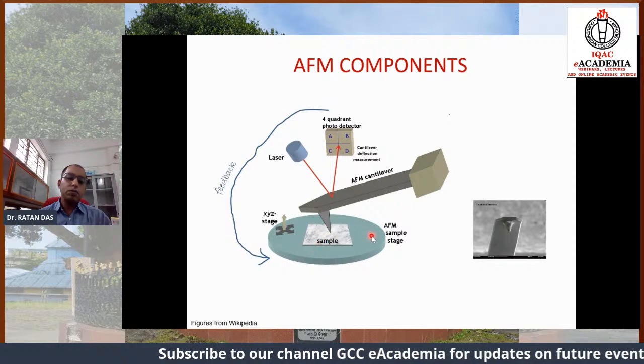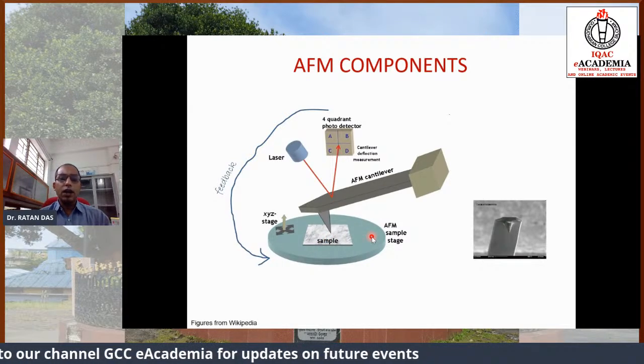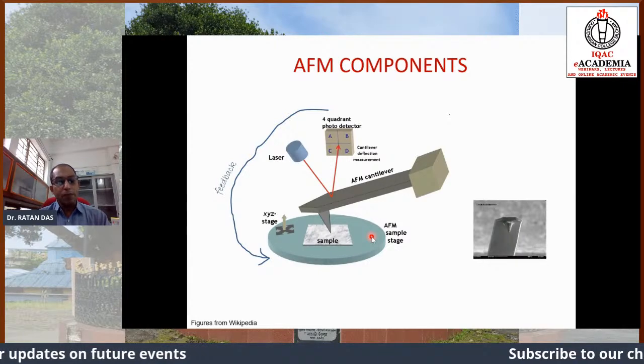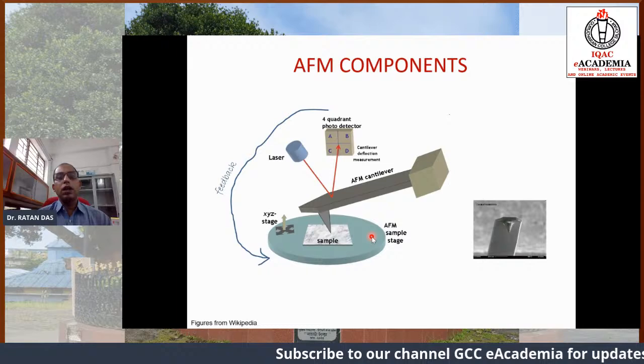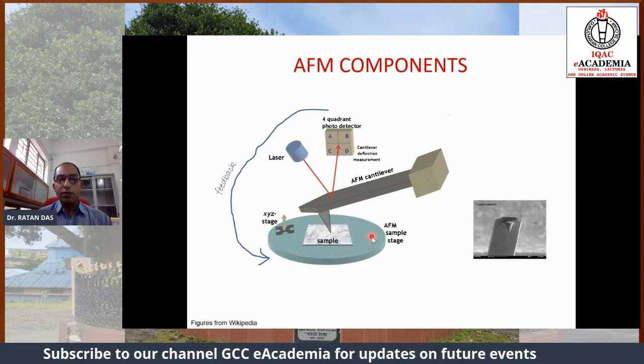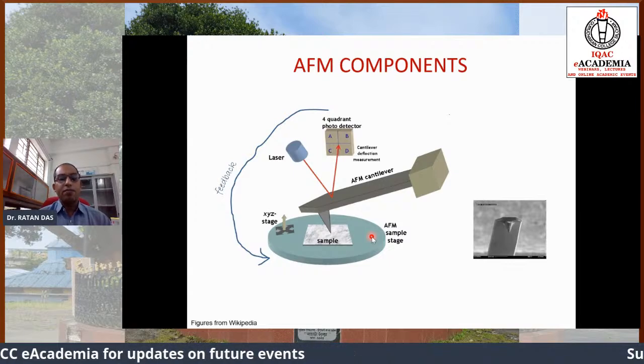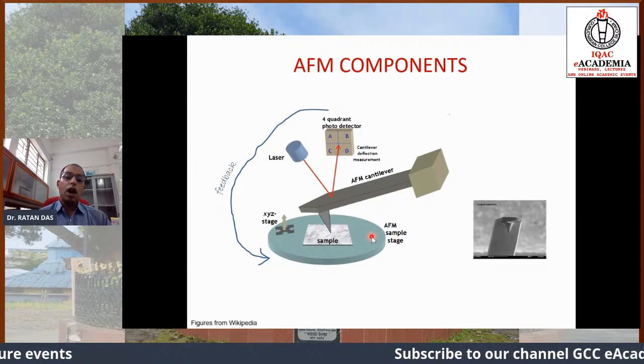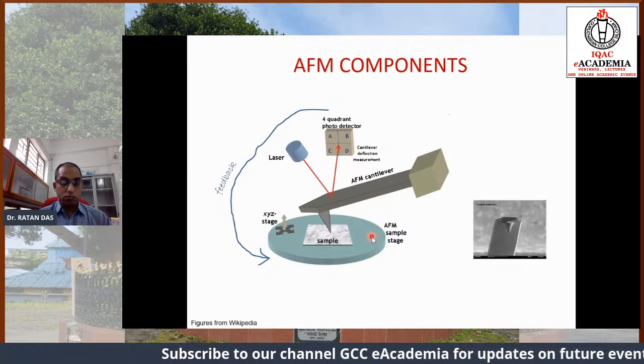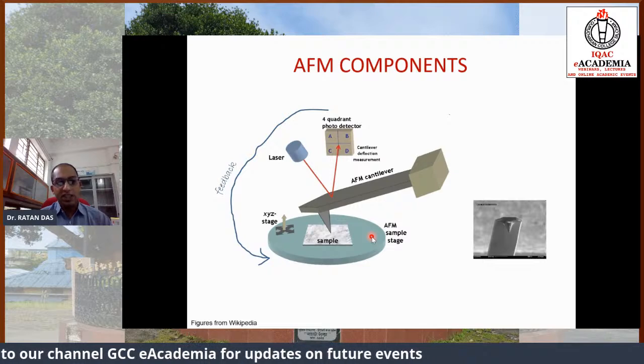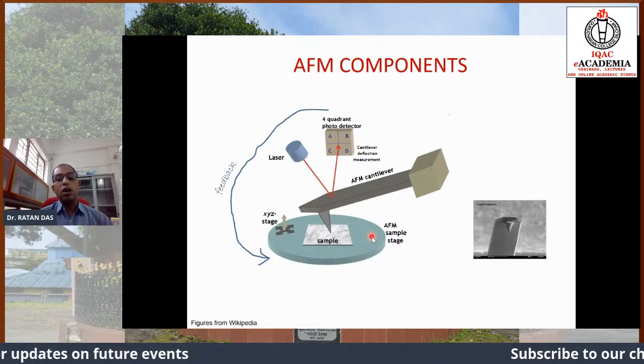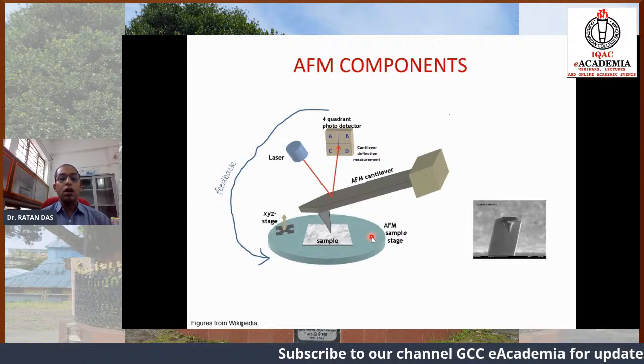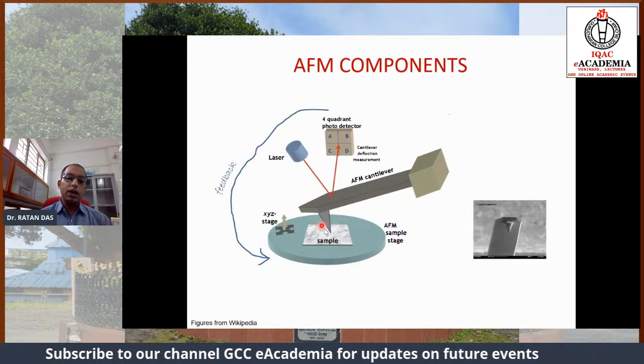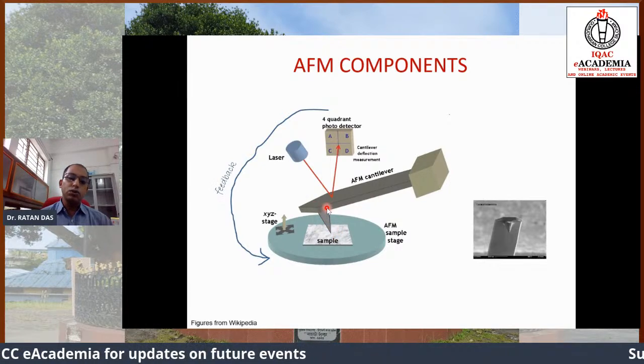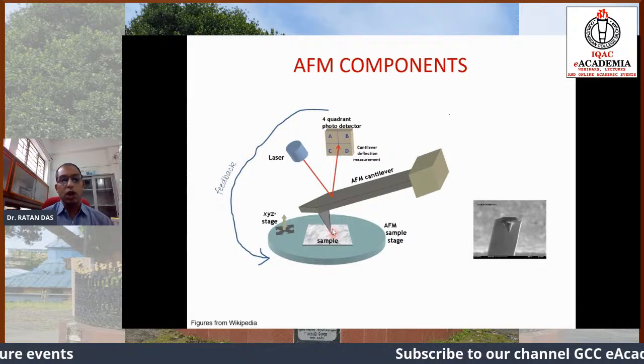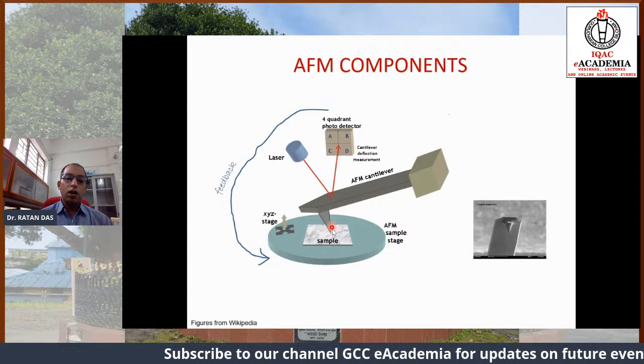But one very important thing I want to say: while studying the AFM analysis, the sample should be very smooth, and that's why generally for thin film structure analysis we use the AFM study. Out of our nanocrystalline solution sample, we prepare a thin film of the solution, and after drying we study the AFM analysis of that sample. The cantilever may touch the sample, or may not touch the sample.